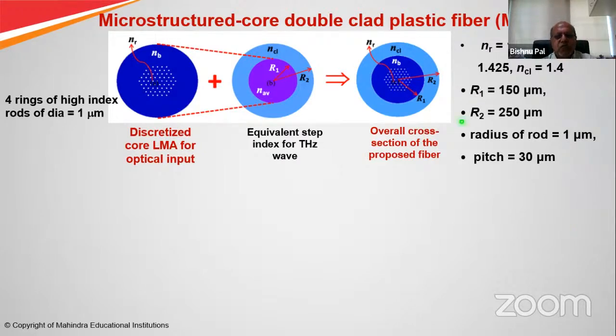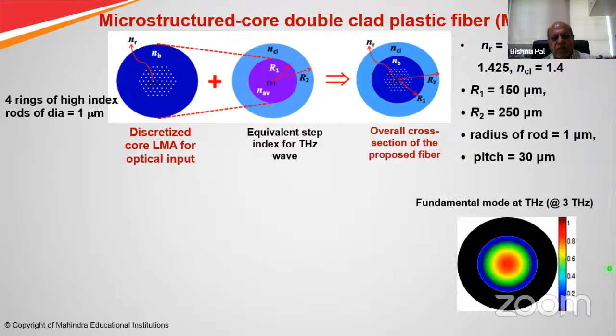These are the parameters. The refractive index of the different regions: 1.425 is the highest region, which is surrounded by 1.44 and 1.4. And these are the radial dimensions of the different regions. With this structure, this is the calculated mode field pattern at the terahertz frequency of 3 terahertz. The mode is confined in this central region, and these are 4 rings of higher effective index at 1 micrometer diameter. Effective area is 30,000 micrometer square at the pump wavelength, and it assumes an effective area of 78,000 micrometer square at the signal wavelength.